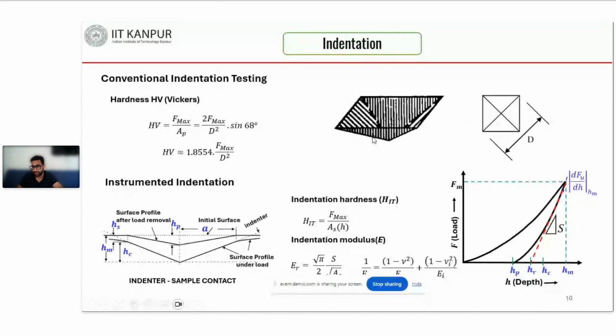This is the impression made on the surface, and if you see the periphery here, it's a square with a diagonal d, and this area will be equal to d squared by 2 into 1 upon sine 68 degrees. Sine 68 degrees is for half of this face angle, and when we calculate it, it becomes 1.855 F upon d squared.